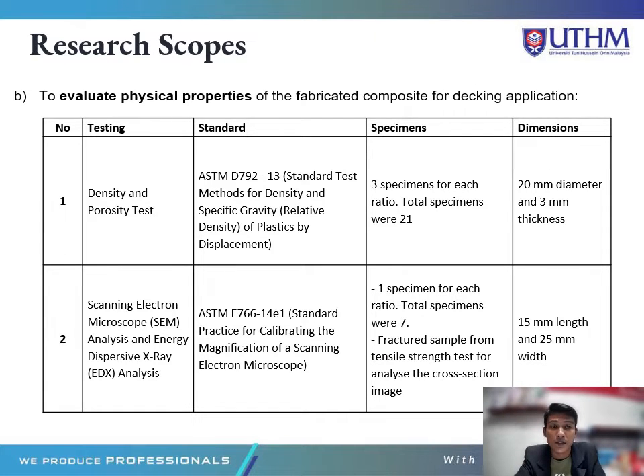To evaluate the physical properties of the fabricated composite for deck panel application, the physical properties will be evaluated using two types of tests: density and porosity, and also SEM analysis. For density and porosity, I am using ASTM D792 as a standard, with 3 specimens for each ratio, a total of 21 specimens, each 20 mm in diameter and 3 mm thick. For SEM, I'm using ASTM E766-14e1 for the standard, with one specimen for each ratio, a total of 7. Fractured samples from the tensile strength test are used to analyze the cross-section image. The dimension for SEM analysis samples will be 15 mm length and 25 mm width.